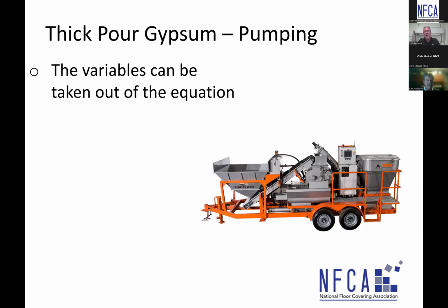And then a third option of taking variables out of the equation is a very sophisticated pump. This gets used out on sites. We've seen these where you're putting the right sand into a hopper, and you're putting the gypsum into a hopper, and then the pump itself is taking the right amount of sand by weight and the right amount of gypsum by weight and getting that blended together. And then the pump is also metering the right amount of water.